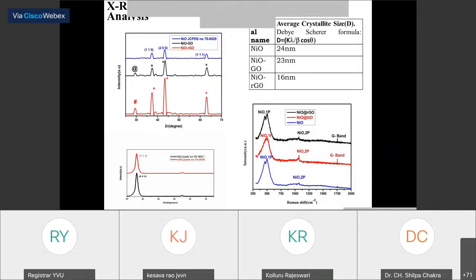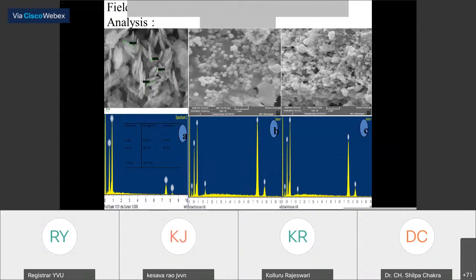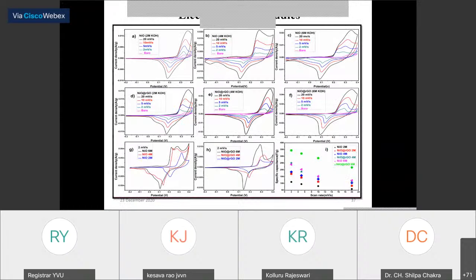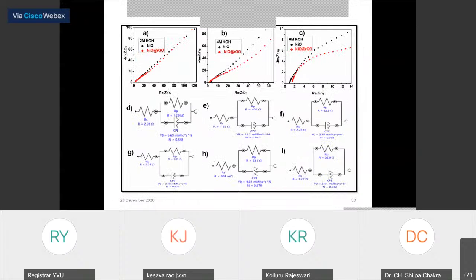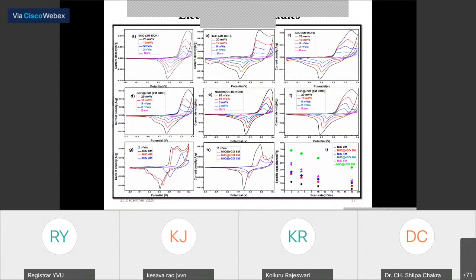So the average crystallite size and G band and D bands are observed using the Raman. And from scanning, we have got the flakes-like structures, and using EDAX, we have confirmed the composition. And when you come to the electrochemical behavior, this increased due to the nano size and high specific capacitance area of nanocomposite structures. In this current study we have done with three molarities of the electrolyte, KOH.